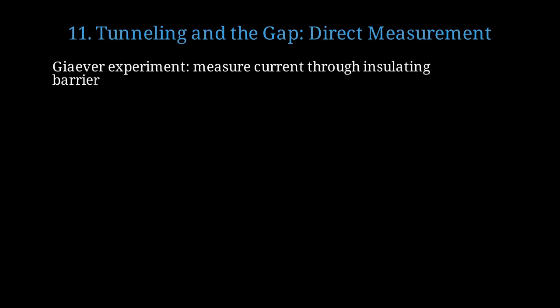Electron tunneling experiments provided direct verification of the energy gap. Giaever's tunneling experiments measured current through a thin insulating barrier between normal and superconducting metals. The tunneling current is proportional to this integral over the superconducting density of states Ns times the difference in Fermi functions. The superconducting density of states shows characteristic peaks at plus and minus delta with zero density inside the gap. These tunneling measurements directly confirmed the existence and magnitude of the BCS energy gap.